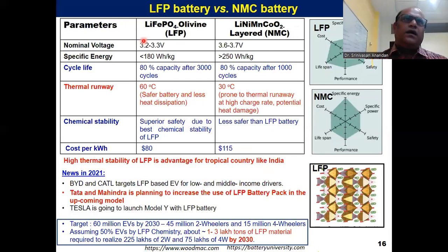There are two well-known cathode chemistries used in lithium-ion batteries. One is LiFePO4, the other is NMC. The energy density of LiFePO4 is about 180 watt-hour per kg, whereas NMC energy density is about 250 watt-hour per kg. This is because the LFP cell voltage is only 3.2 volt, whereas NMC voltage is higher compared to LFP. That is the reason it shows higher energy density. If you have high energy density, you have a long driving range, and you may use it for that.